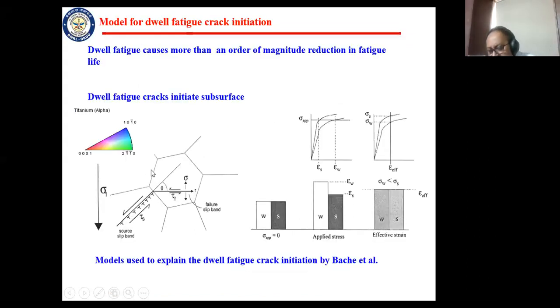Now, why dwell fatigue cracking happens is explained by Bache, although this explanation is by no means complete, but it is there because of the lack of clearer explanations. If you have a textured material, one where you have easy deformation and easy slip, and you have an orientation which is difficult to deform, that is, where you have to deform in the c+a region, then what happens is it deforms in the soft region, unloads onto the hard region, that is deformation-wise hard. It adds on to the applied stress, and it reaches the fracture strength before it reaches the deformation stress, and so it starts cracking.